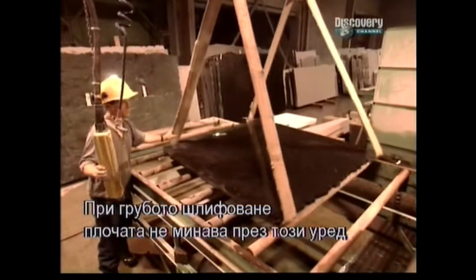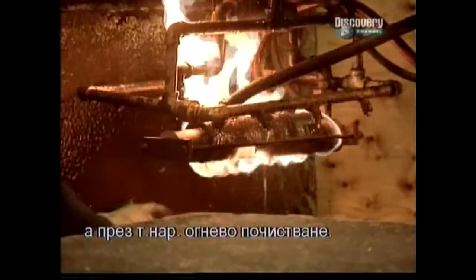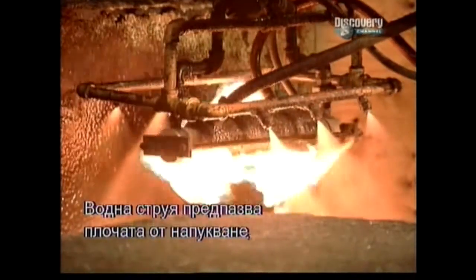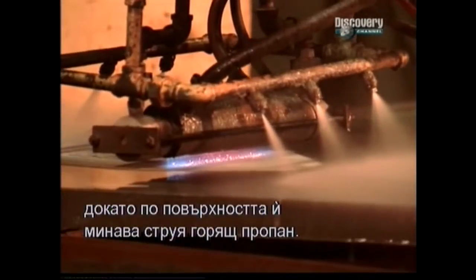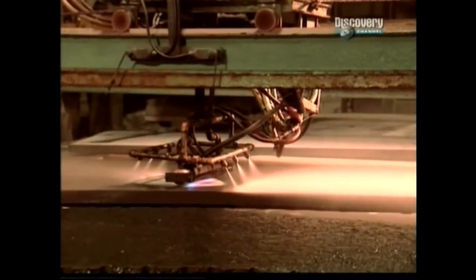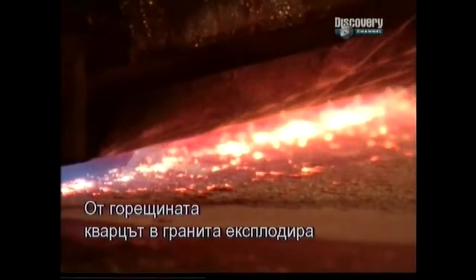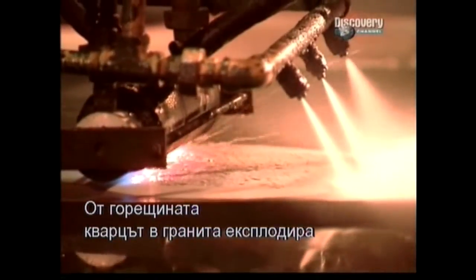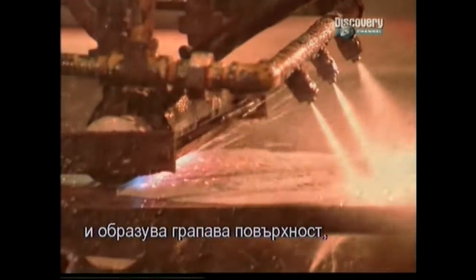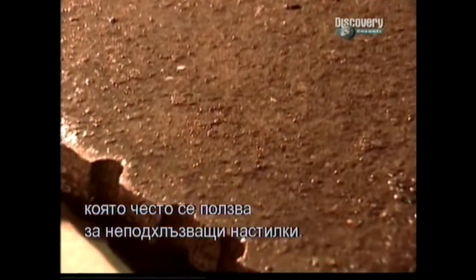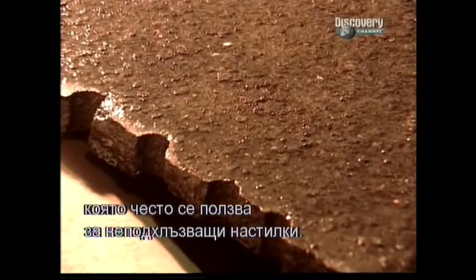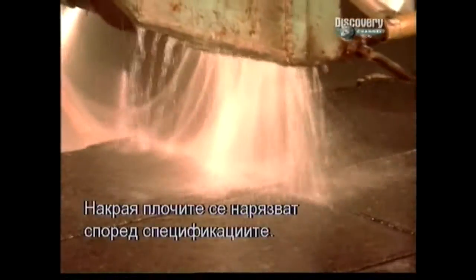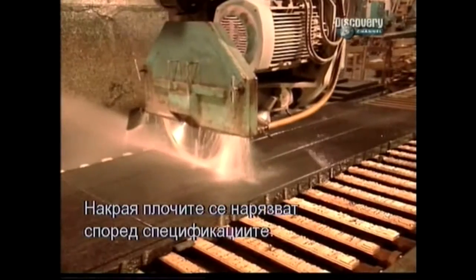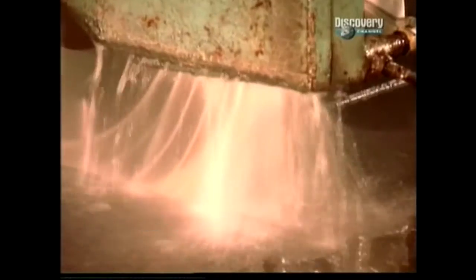For a rough finish, slabs skip the polishing line altogether and instead go through a process called flaming. With a stream of water to keep the slab from cracking under the heat, a propane flame is passed across the surface. This intense heat makes the quartz inside the granite explode, creating a rough surface. This is often used for non-slip flooring. After the finish, the last step is to cut the slabs to specifications.